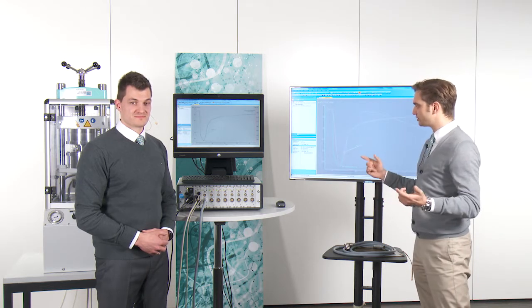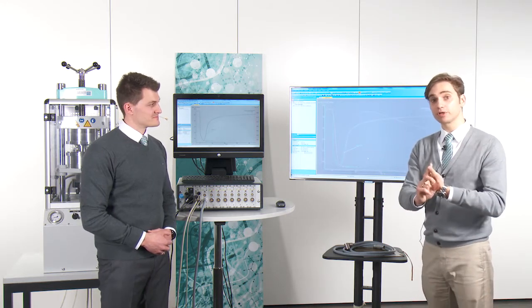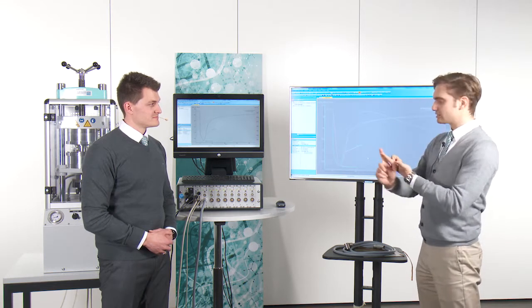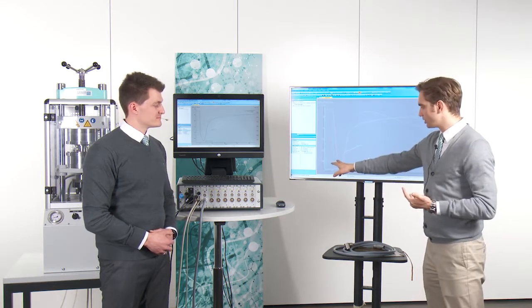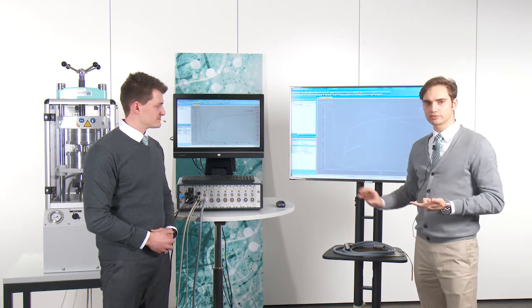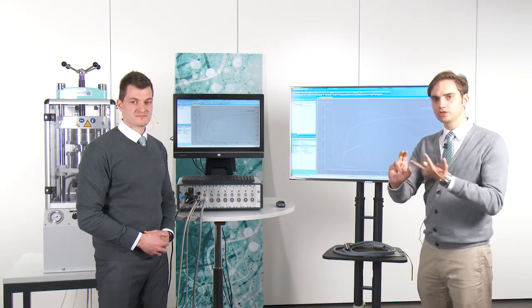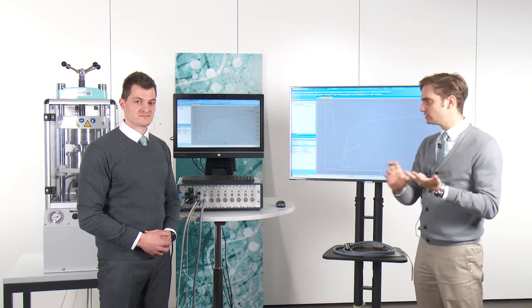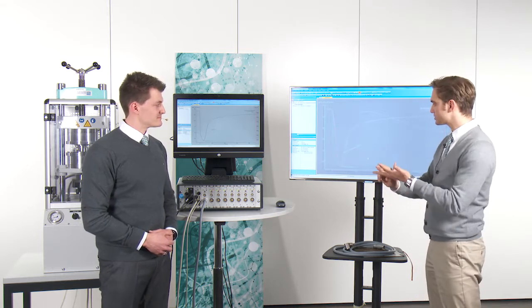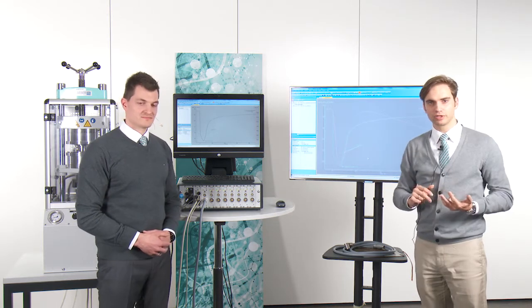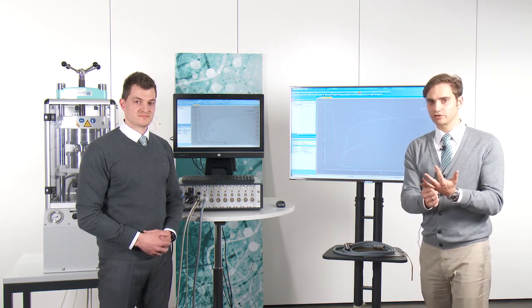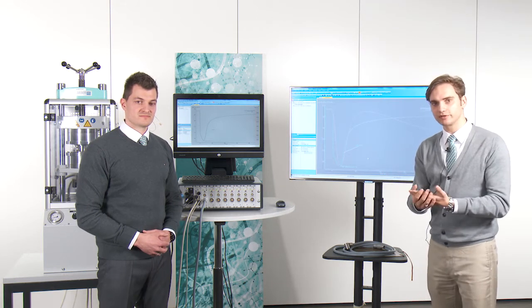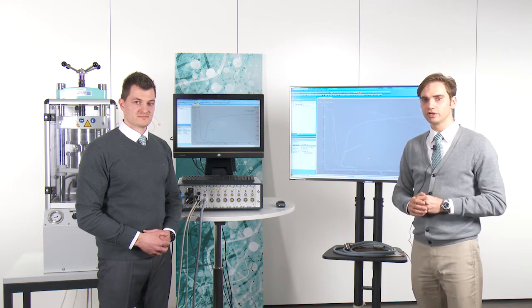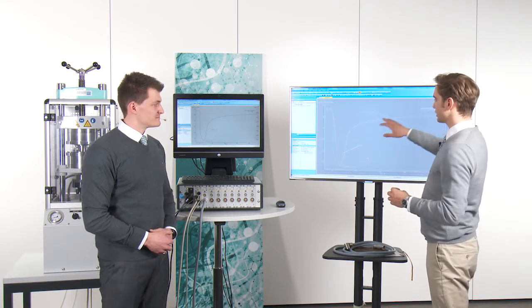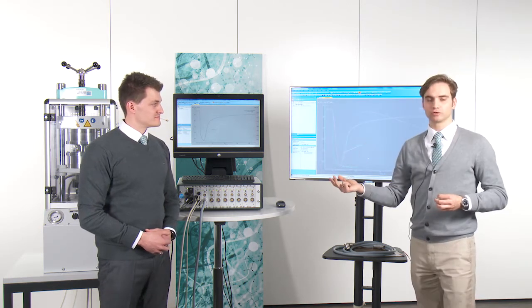We could learn that you get a sensor for the sample arrival. You get a sensor for the part that correlates to the lowest viscosity. You get a sensor for the reactivity, the slope here. And you get a sensor for the inflection point, or the gel point, and still you can trace the entire curve of the curing as it goes along inside your mold.